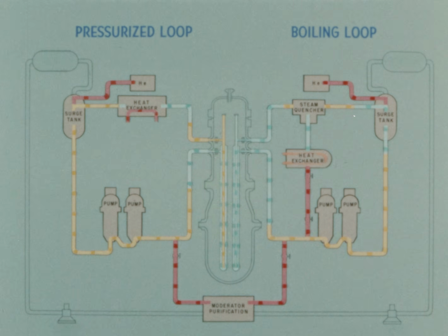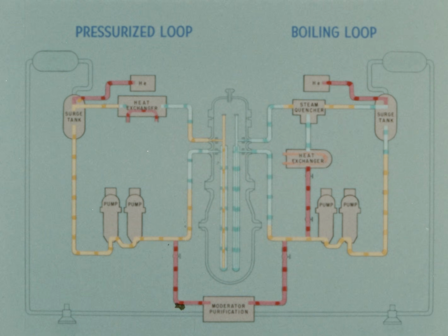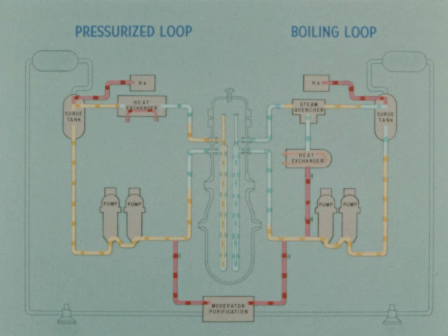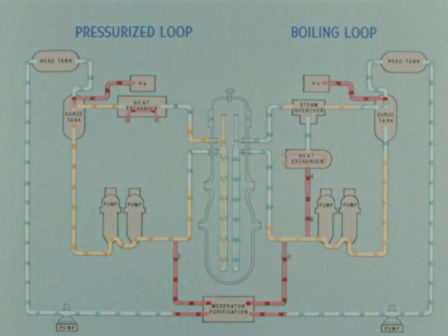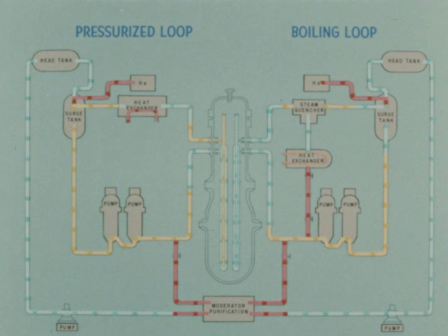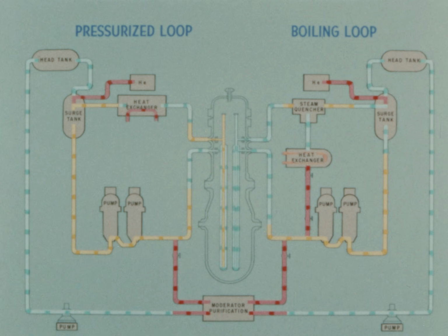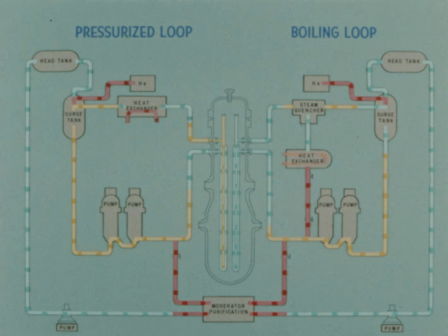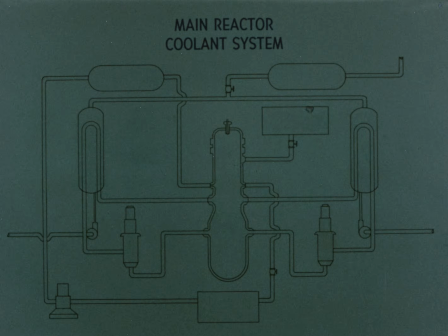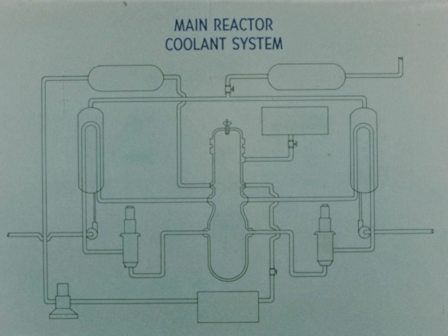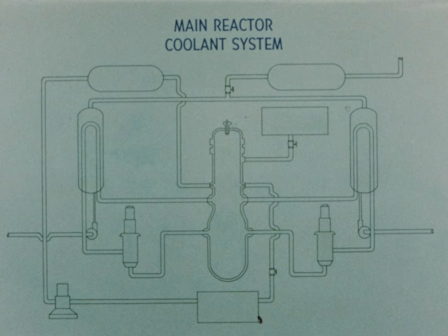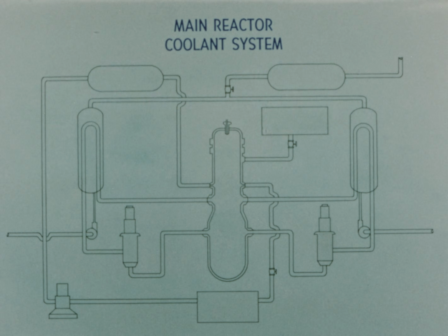Purification of the heavy water in the isolated coolant loops is accomplished in a common system. High-pressure makeup pumps feed separate head tanks for each loop and inject clean, heavy water into the systems. The two coolant loops of the main circulating system, including the steam generators, are fabricated of carbon steel.